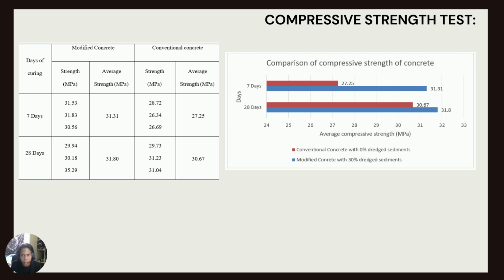Okay, next for the compressive strength test. Both types of concrete showed an increase in strength from 7 days of curing to 28 days of curing. On the 7 days of curing, the graph showed that the 50% replacement obtained the highest compressive strength reading, which is 31.31 megapascal, while the conventional concrete obtained 27.25 megapascal, which is lesser than the modified concrete. In contrast, at 28 days of curing, the highest compressive strength reading for modified concrete is 31.8 megapascal, while the reading for conventional concrete is 30.67 megapascal. It can be observed that the modified concrete has higher compressive strength for both days compared to the conventional concrete.